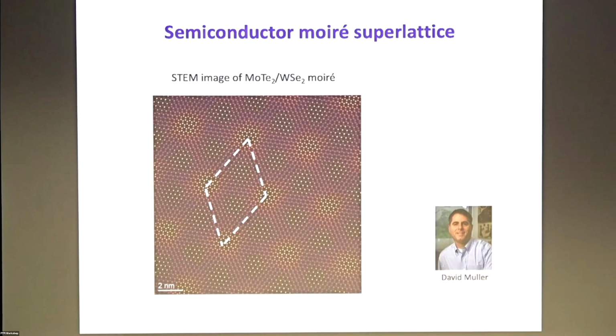You can actually really see it in a STEM image. This is a STEM image in collaboration with David Muller's group at Cornell. Looking at this particular combination, which is a heterobilayer that has 7% lattice mismatch, you can see that the small dots are the real atoms, but on top of that, you can also see the emergence of a pretty regular moiré lattice, and that's the unit cell of the moiré lattice.